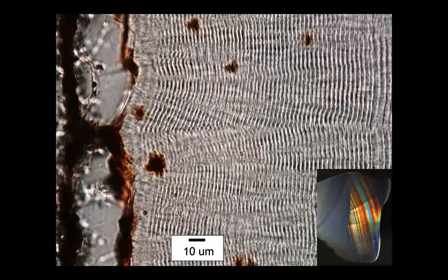When we look at an iris agate with a petrographic microscope, just a light optical microscope, we actually see fringes associated with this iris banding really clearly. You see them here as these vertical striations, and the distance between these striations is on the order of half a micron to maybe a couple of microns or so. And they've been documented to repeat up to 17,000 times in a single specimen.